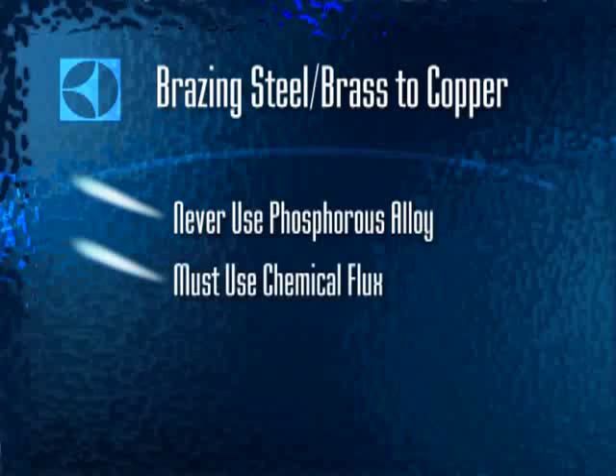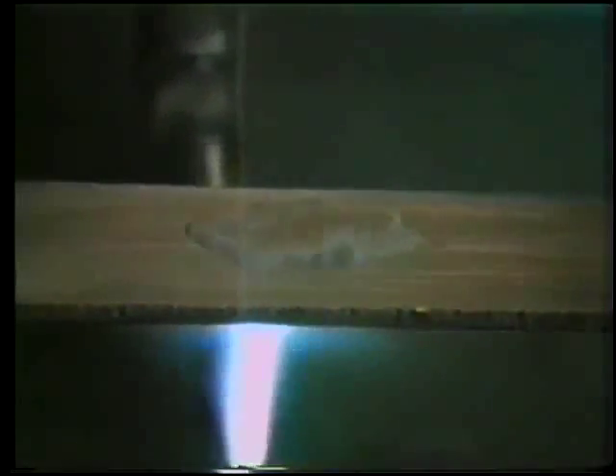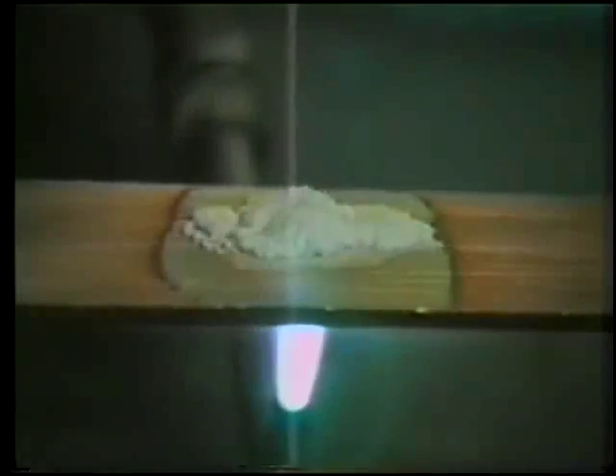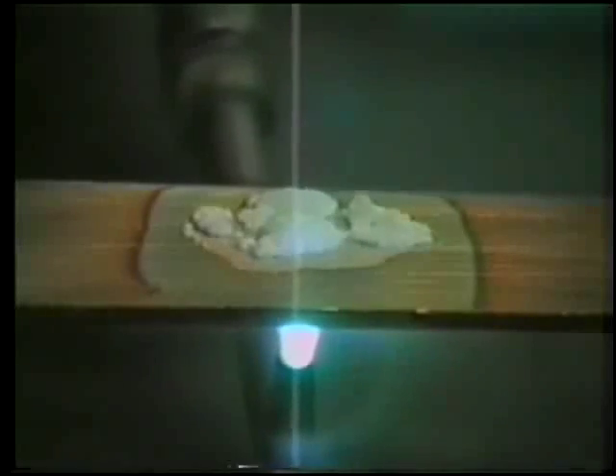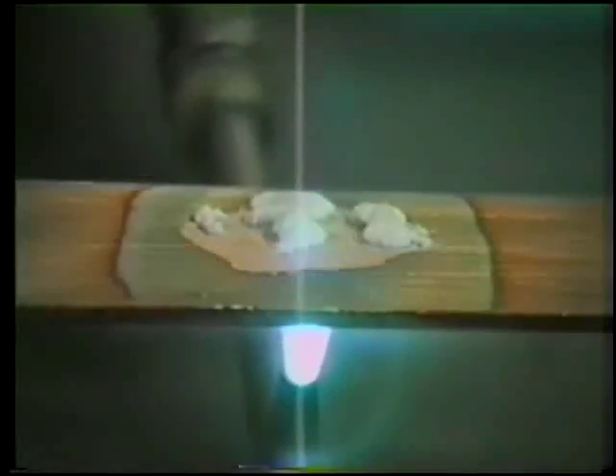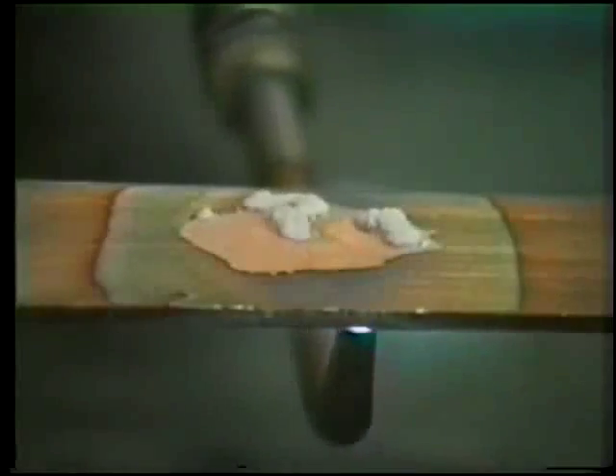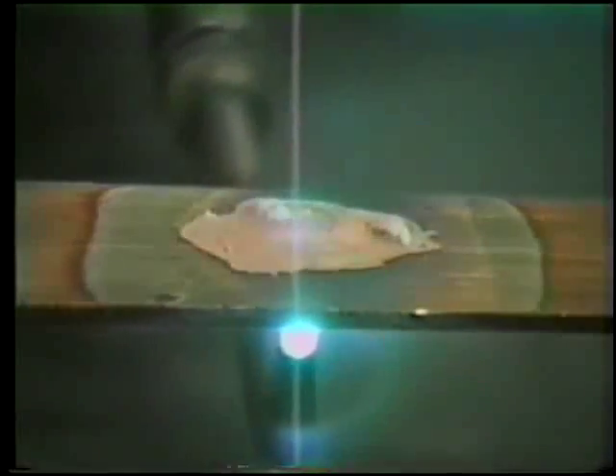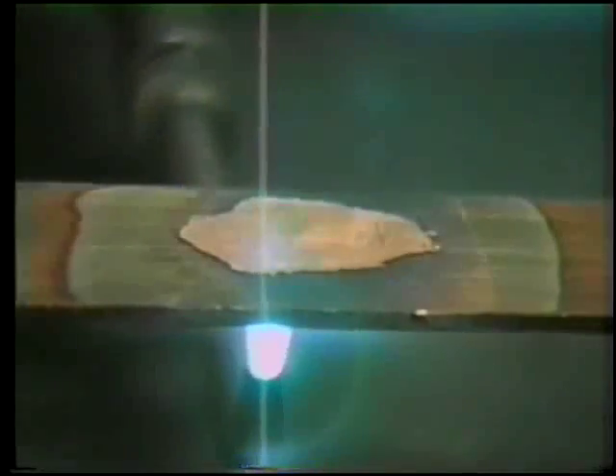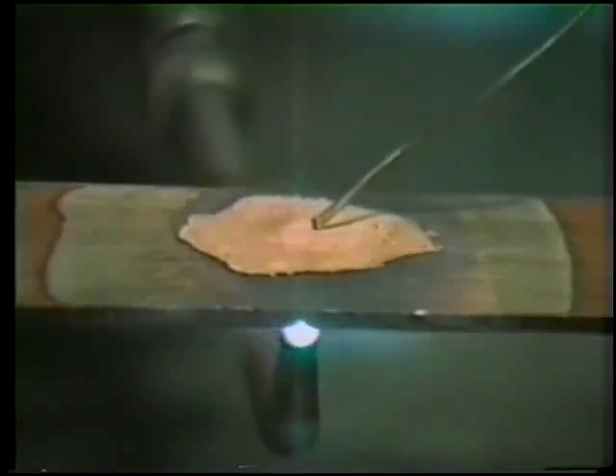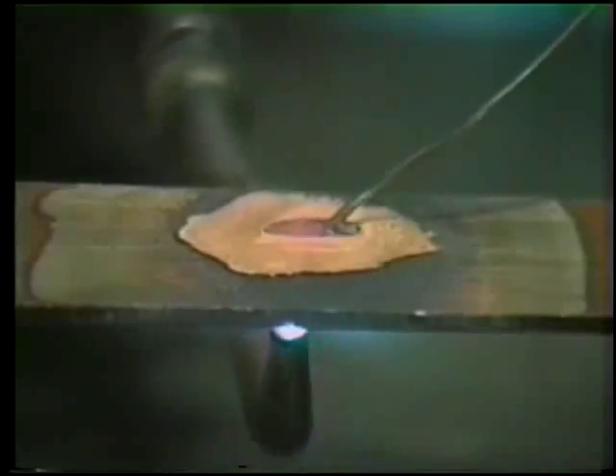You'll need to use a chemical flux with these base metals to dissolve oxides and prevent them from reforming during heating. Flux goes through changes during heating, and these changes are a visual clue to when parts are at brazing temperature. At 212 degrees Fahrenheit, the water boils off. At about 600 degrees Fahrenheit, the flux begins to bubble, and at 800 degrees Fahrenheit, it starts to melt and become active. Notice the clear protected area under the flux. At approximately 1100 degrees Fahrenheit, the flux is clear, and we're ready to apply our filler metal.